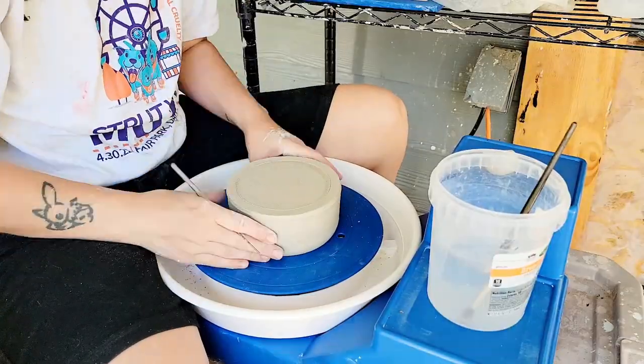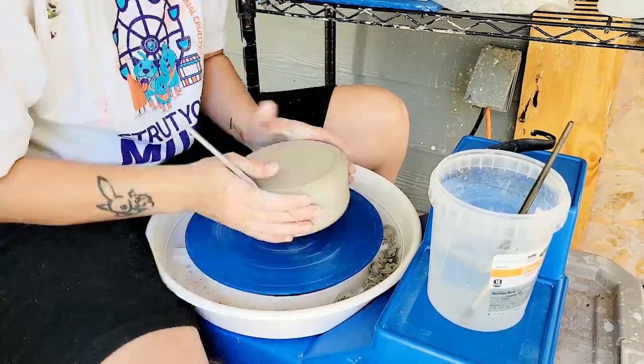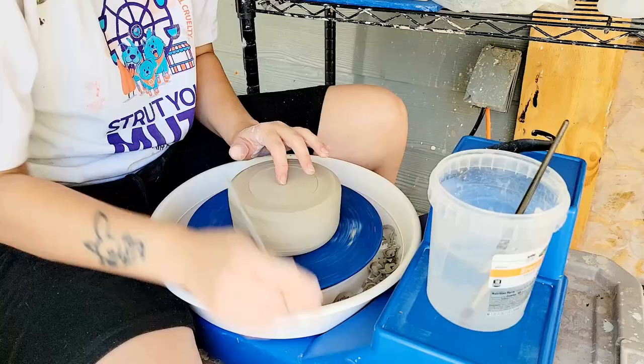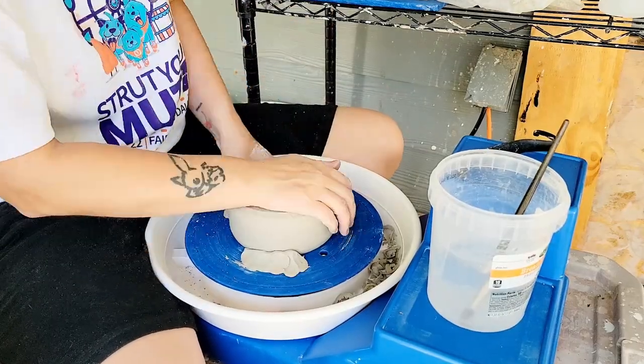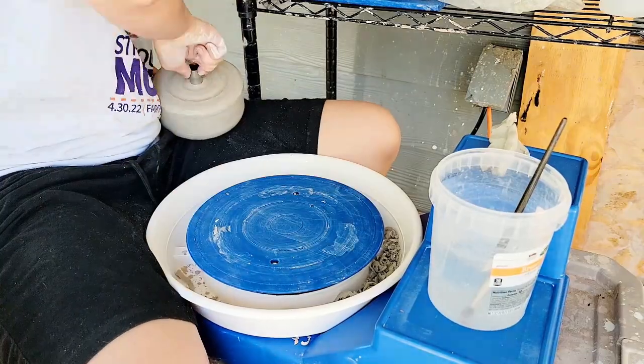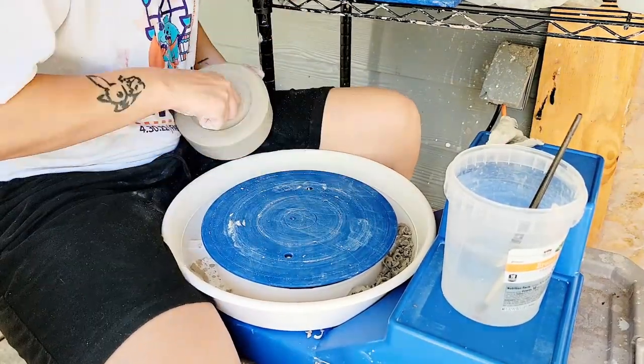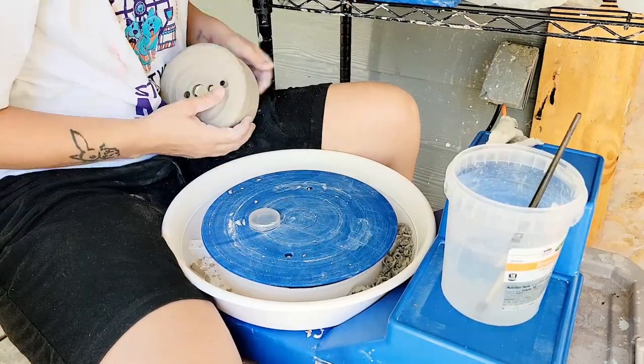Trimming is very much like trimming porcelain. At leather hard, it's a very thick, dense body. If you try to dig too deep, you can catch the pot on the wheel and pull it off, distort it, or give it a crack — it likes to crack. The best approach I've found is to have a very sharp tool and to take the trimming in tidy and delicate ribbons.